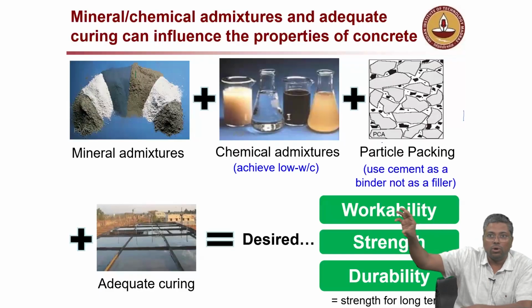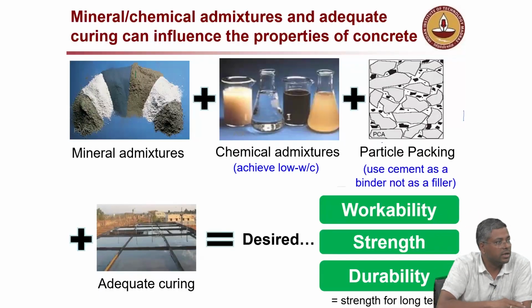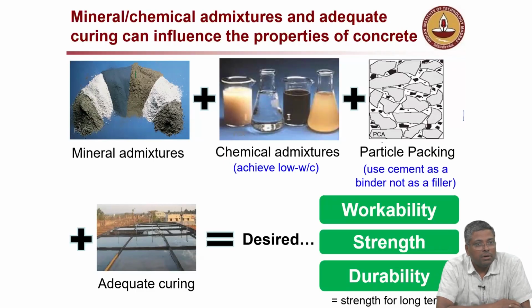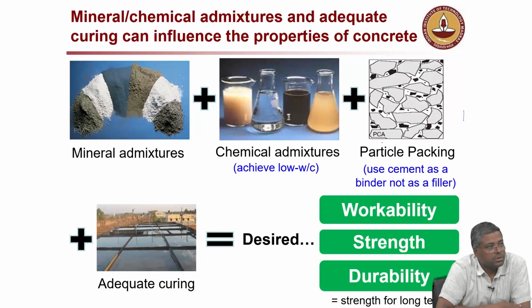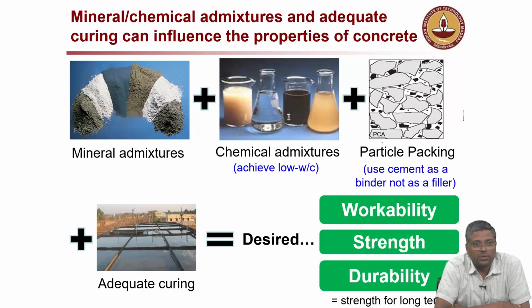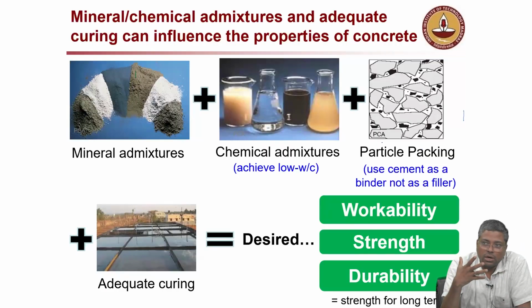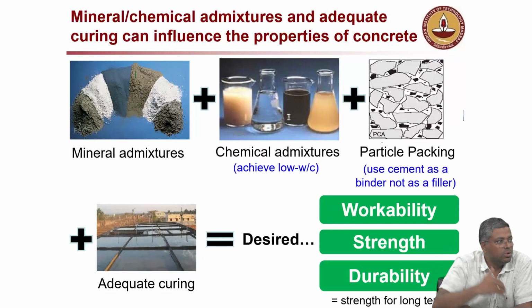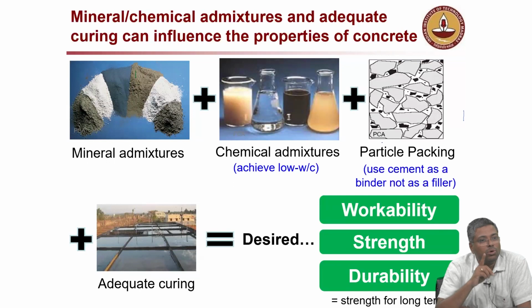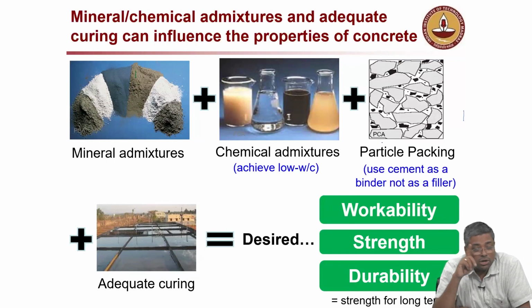To the top 3 rows which you see, those materials in right proportion, we can get enough workability, strength. But if you want really durability, you need to also cure the material very well. Otherwise, it will be like on paper, you will have every material, but it will not really show what you really want. And why I am saying this is, it is not that for strength you don't need curing, but strength is not very sensitive to curing. In other words, if you do not cure a concrete, let's say, not really the way you want it, it may still show adequate strength, but not durability.